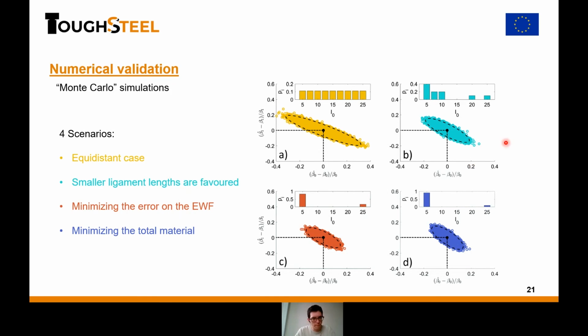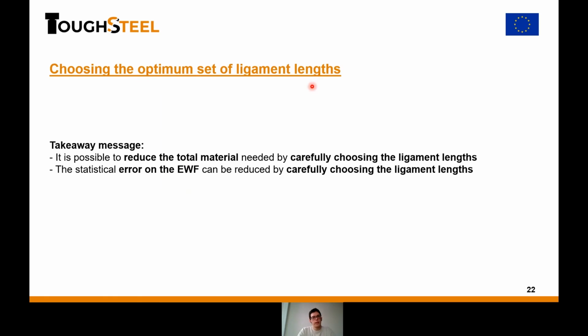So the takeaway for this part is that, yes, again, it's possible to reduce the total material needed by carefully choosing the ligament length. But the second thing that is shown is that even if you don't adapt the specimen size to the ligament length, you can still improve your error on the essential work of fracture by choosing carefully the ligament length.